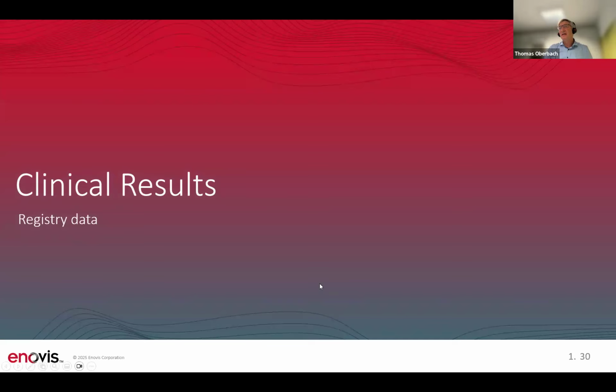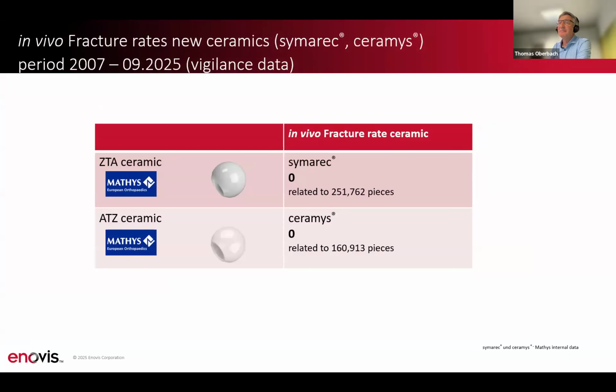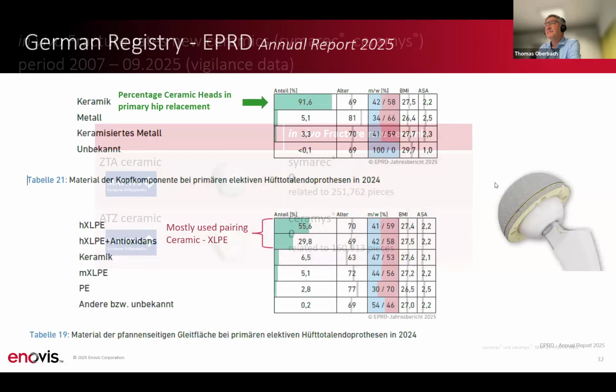Yeah. What about the clinical data, registry data of the implants? You remember the in vivo fracture rate of the alumina heads was in the range of 0.028. And when we look on our vigilance data from our post-market surveillance, then we look back on about 410,000 implanted pieces in total made of Symarec and Ceramys, and we didn't found up to now, and this is a very, very good result for us, we didn't have a fractured head. And so, in our opinion, the problem with in vivo fractures for hip heads is solved with the new ceramic materials which are available on the market.